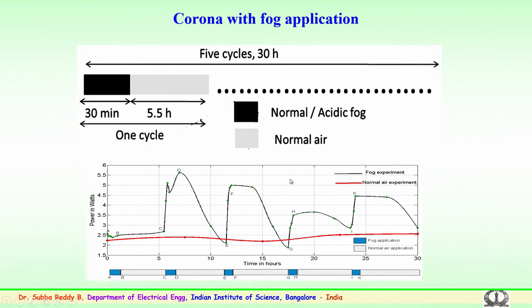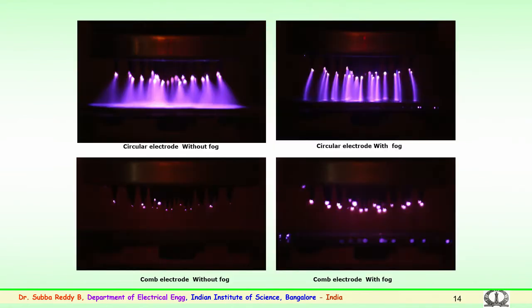but in case of fog or acidic fog, you can see the increase in magnitude of the power over a period of time. This graph is shown for the normal fog conditions. So, a comparison is made between the dry condition and the fog, where the magnitude increases. The power consumed by the sample, the power flow into the sample, is much more in case of fog or acidic fog. This will create surface changes over a period of time in case there is a mist with the corona discharges on the surface for a long period of time.